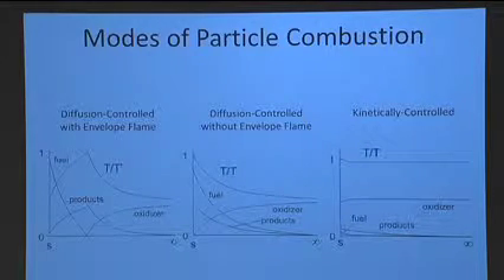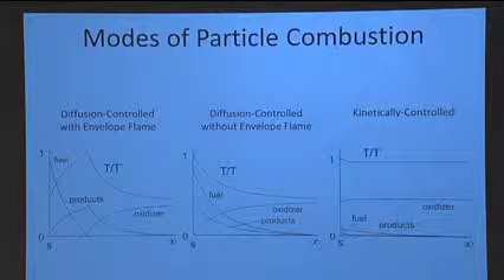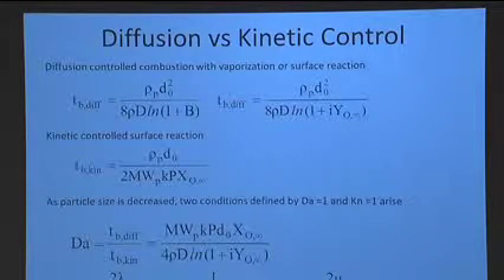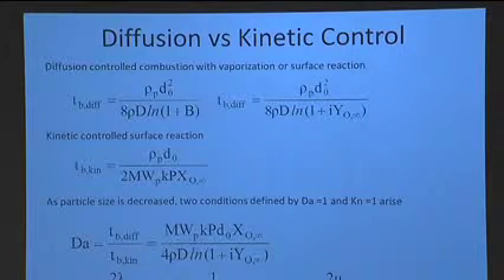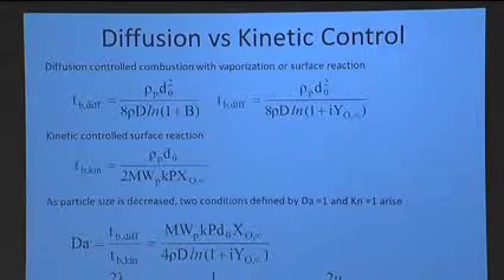Well, if I look at these systems, and this is what's been done traditionally in textbooks, I can go back and solve the one-dimensional conservation equation for species and energy, and I can come up with solutions for what these profiles might look like. And once I have those profiles, I could actually calculate burning times, how fast these particles might react. And if you do that, what you'll end up with is some of the results I show here. Again, just looking at two extreme cases. And again, I just want to pick out some of the qualitative trends, and these are sort of the trends that you should go away with. But if you look at, say, the diffusion controlled case, and again, you go through and you integrate the equations, you'll get an equation for the mass burning rate. I can integrate that equation from the initial size of the particle to letting it disappear, and I can then calculate a burning time.